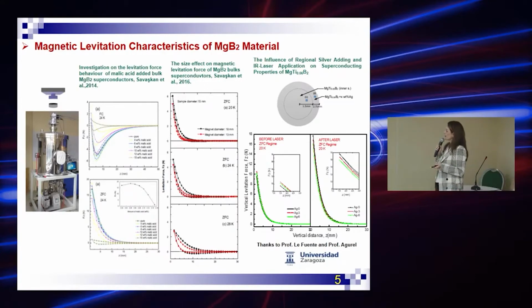Firstly, we investigated the effects of malic acid addition on magnetic levitation force of bulk MgB2, and we used the two-step reaction in situ solid method, and we observed that reasonable addition has a positive effect on magnetic levitation.